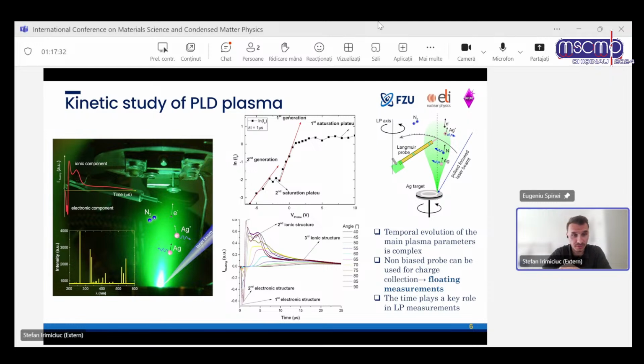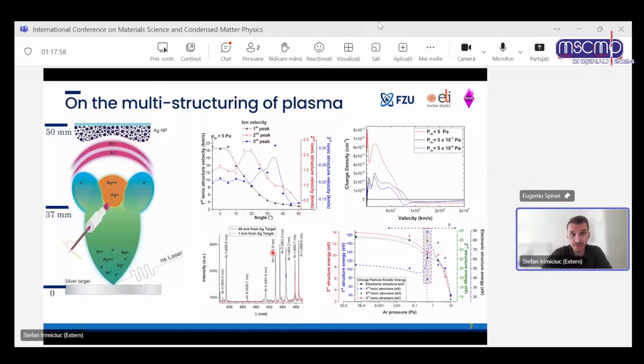So if you look here, this is the ionic current in the plasma. You see you have really fast electrons traveling in front of the plasma, which will be at the front of the plume here. And then you have ions, which arrive with different times of arrival, which means they have different kinetic energy, which for laser-produced plasma means different ionization states. For the proof of concept, we used silver, and all our diagnostic tools come into this angle distribution. So we have multiple ionization states in the plasma, and they have a different angular distribution. So it's important to know where to put the substrate when we do the deposition. If we put it off axis or on the main axis, different ions will interact with the substrate.